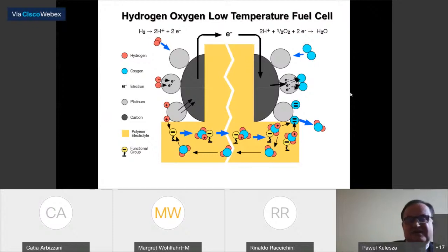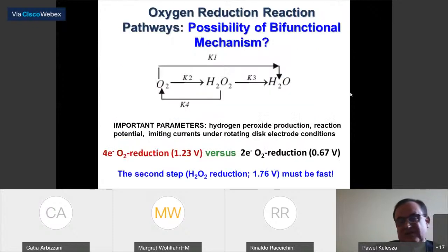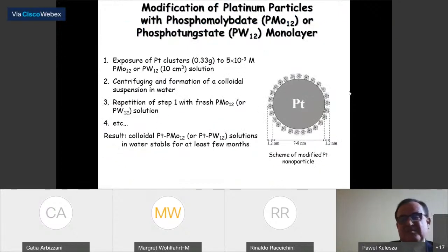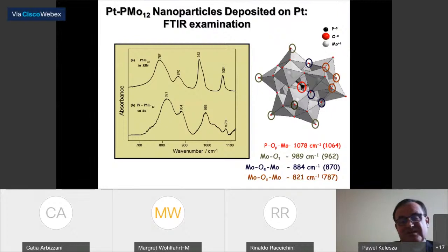low temperature fuel cells. And if I go back to the older research, it's well known we don't want hydrogen peroxide, we want 4-electron reduction. We can get a much better potential and, of course, better stability. At that time, we were working on nanoparticles modified with polyoxometalates. We use them for different purposes. It was actually part of the research also of Małgorzata Chojak, who visited the University of Camerino at that time as a graduate student. Later, other people were coming and pursuing research at both institutions.